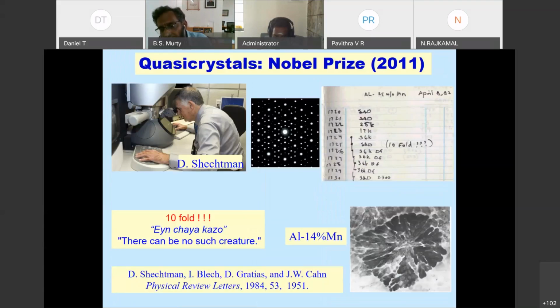In addition, TEM also was helpful in discovering a new type of material called a quasicrystal. In fact, if TEM was not there in those days, the so-called tenfold symmetry would not have been possible to see, because X-ray diffraction typically does not show you that. If you put a quasicrystal through an XRD, a typical powder XRD, you will never be able to differentiate between a crystalline material and a quasicrystalline material.